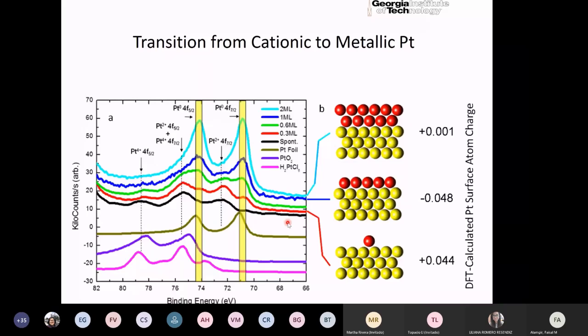In that case, we could see the Auger reaction when the platinum wasn't fully covering the graphene. Let's say a third of a monolayer or 2/3 of a monolayer, we could still see the Auger reaction happening through the graphene. But once we got a monolayer and beyond, then we saw that the Auger reaction disappeared. So that could be a way of getting an average understanding of whether or not you have full wetting. So you have to use different tools, but if you really want to know the spatial distribution of different types of crystallographic structures, your best bet is to do electron microscopy.